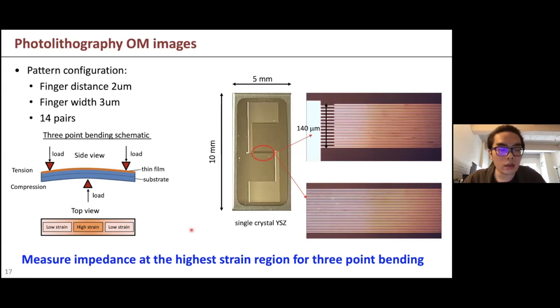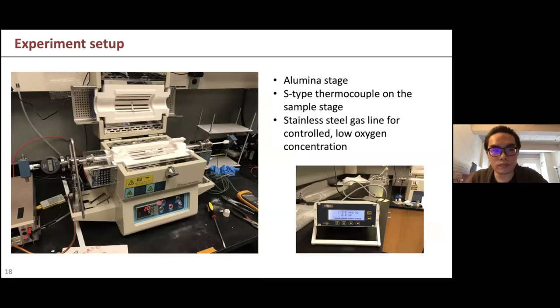So in the end, with this setup, I can measure the impedance, which is the method that we use, and convert it to conductivity, and then in the end get the activation energy at the highest strain region when we use three-point bending. So this is the experiment setup that I want to show here. It is still going on, so I'm not going to go into details.